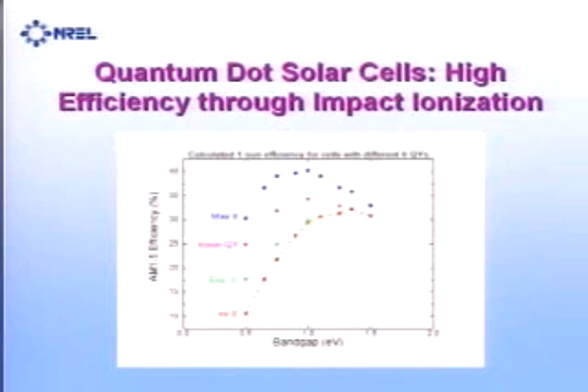And Mark Hanna was doing these simulations, and he showed that you could get an improved efficiency. This is with no carrier multiplication. You just get the normal 30% efficiency. With the experimental data shown in green, it's not optimized because you'd want the band gap to be about 0.5. The bulk band gap of lead selenide is 0.28 eV, but there is some improvement here. And then in the ideal case, where you had that stepwise function, you could get up to about 40% efficiency.